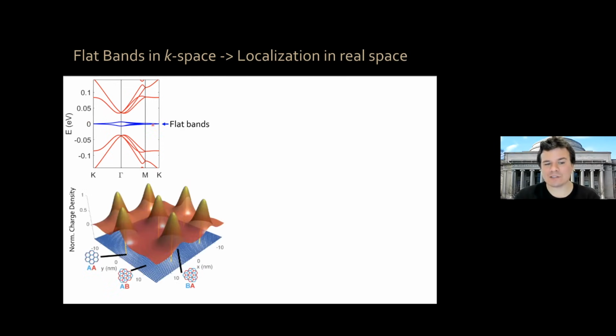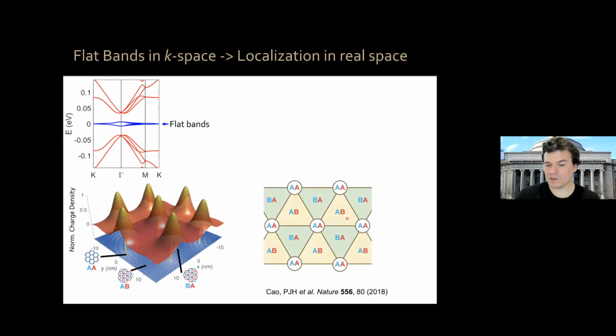So if we place electrons in these flat bands and we look where they like to be, okay, it turns out the electrons like to accumulate in regions which are called AA stacking, where locally the registry between the 2 graphene sheets is such that all the carbon atoms are on top of each other. These regions are separated by regions where locally, due to the small twist angle, the stacking is of AB and BA type. Only some atoms are on top of the other, okay? And those are tunnel regions, regions coupled via tunneling, the AA regions. So from the top, magic angle graphene looks like this. We have these regions of AA stacking where the electrons like to sit.